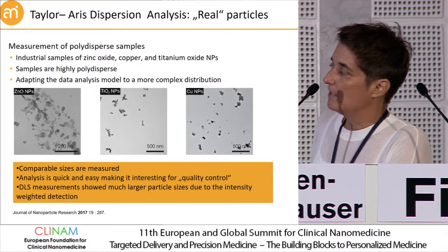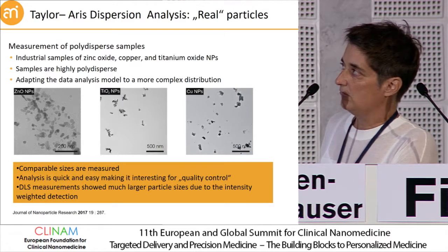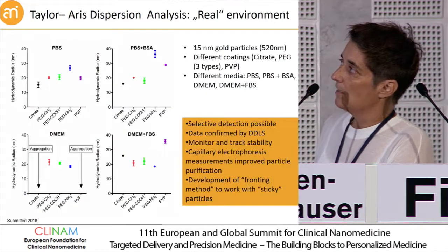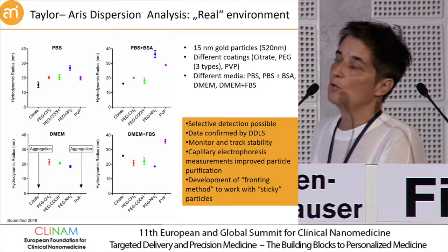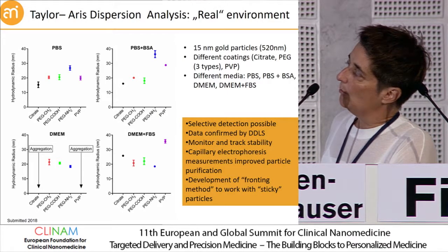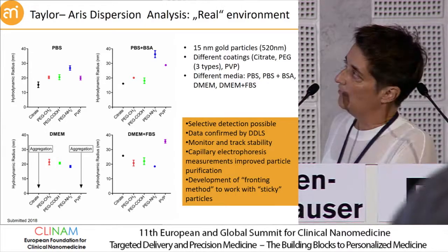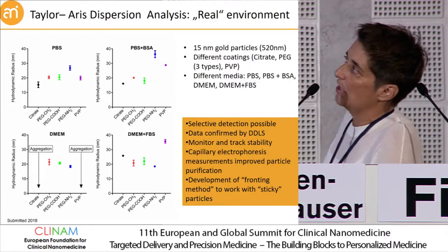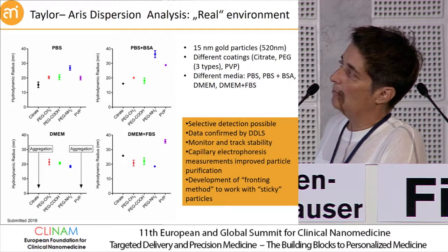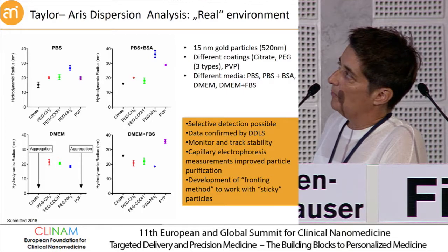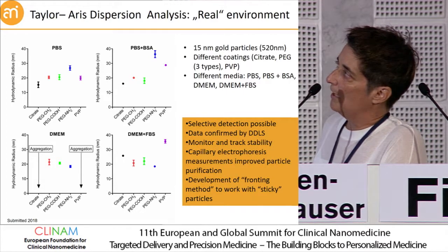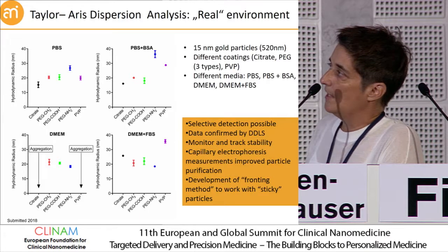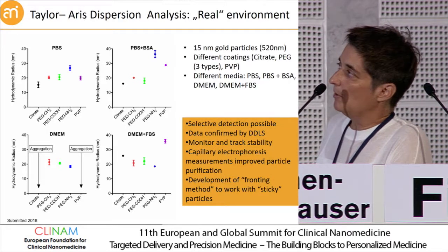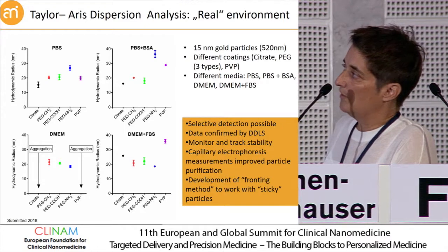So now the question is, do the numbers that we get from that make sense? So what happens if I go back again to my model particles? Again, the gold particles, pretty small ones with different surfaces. And again, like the first image I've shown you, I place them in these different environments: pure PBS, a PBS that we spike with some BSA, a typical representative of cell culture medium, and then one where we add the serum. All this is very reliably measured and easily compared to what we've done with DDLS.